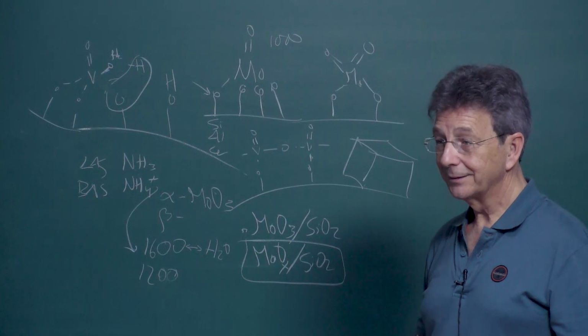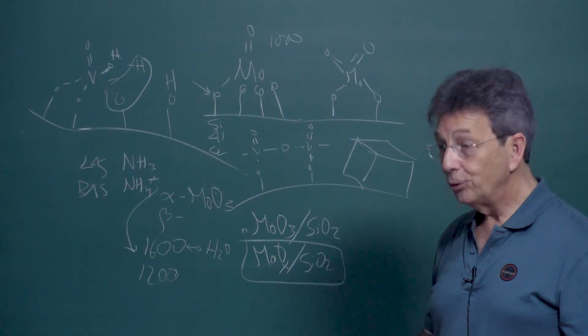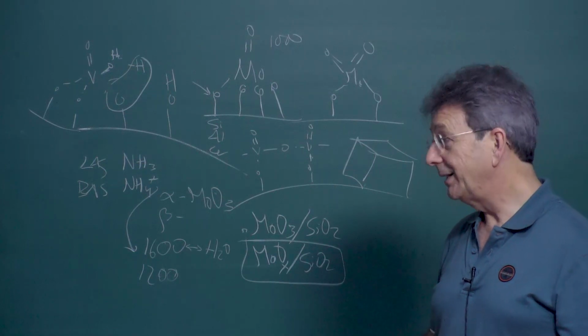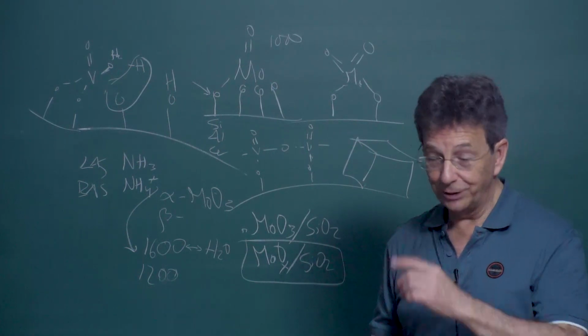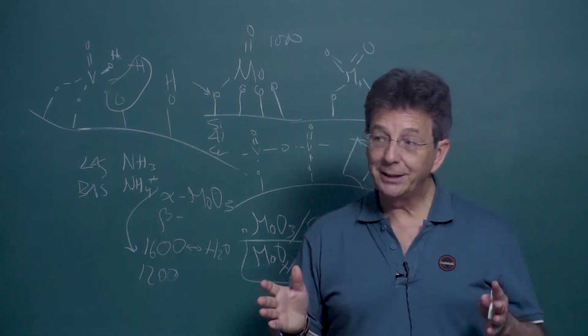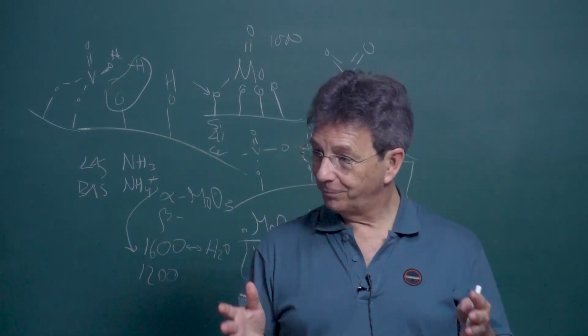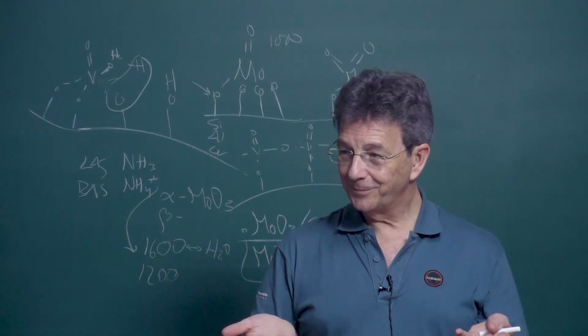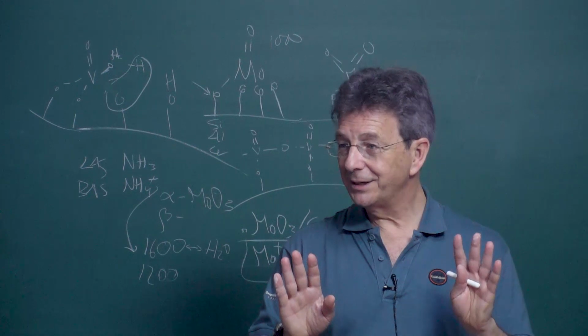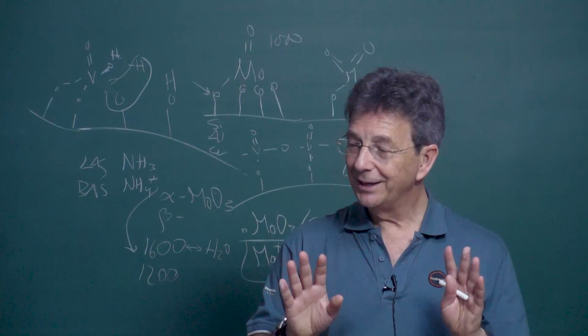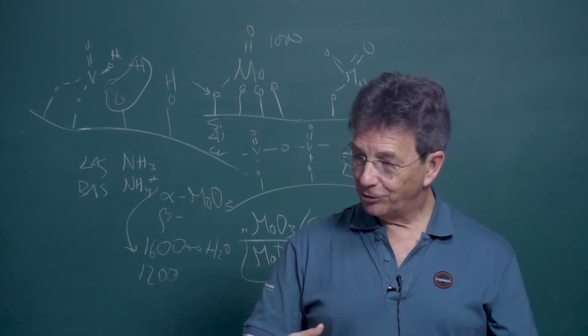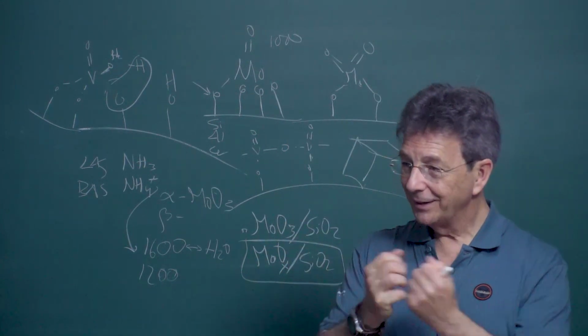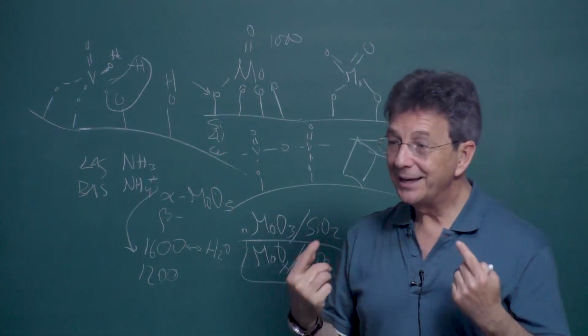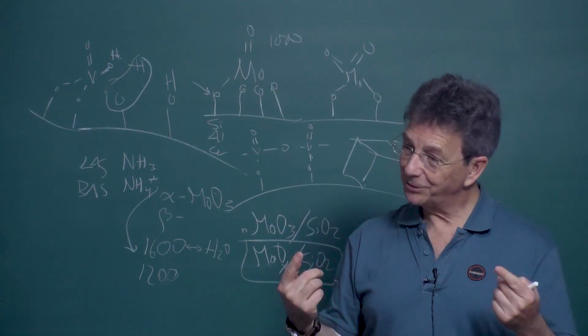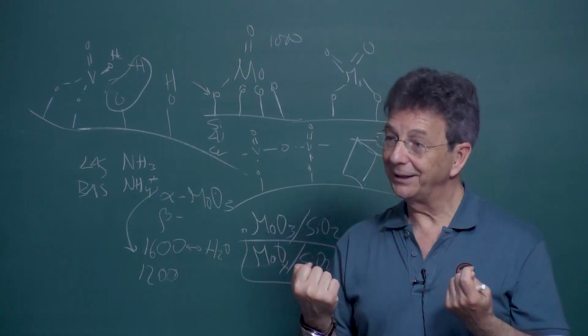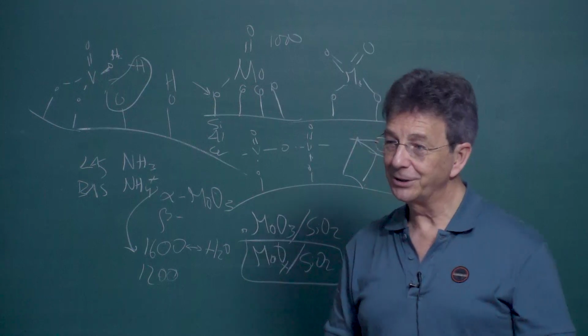Okay, we can also do it at a high temperature so that we can remove the moisture. You can do a high temperature, yes. And typically, one of the things that is also made, because this point of the temperature is a very good one, is that you can make an infrared spectrum of chemisorbed pyridine or ammonia and increase the temperature. And then you will see whether the Brønsted or the Lewis are leaving before or after. So you can see this Brønsted site is stronger than the other one, because even if I increase the temperature, it's still holding it, and the other one is losing it. So you can also tell the evolution of the pyridine Brønsted and Lewis against the temperature, because this will tell you how strongly they bind. So then you get additional information from there.